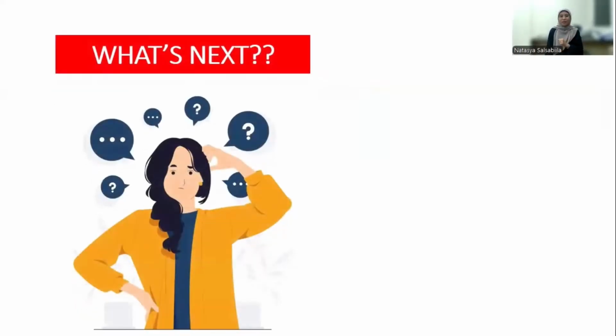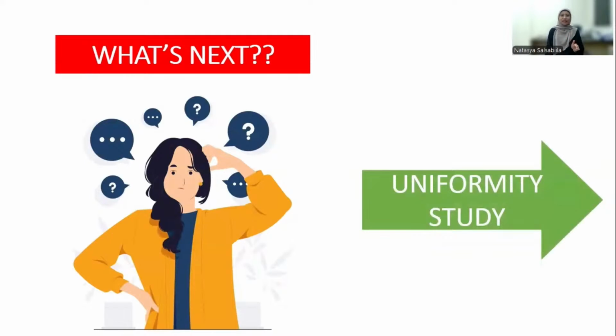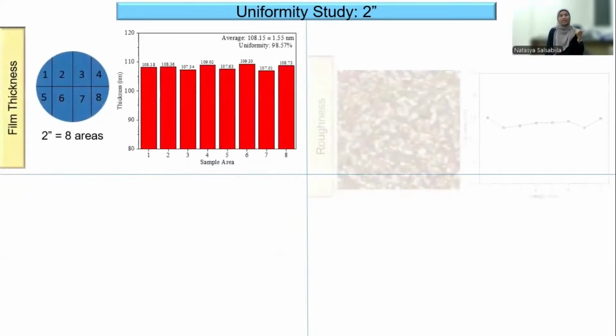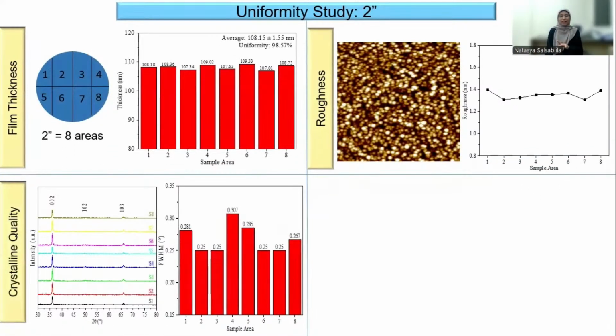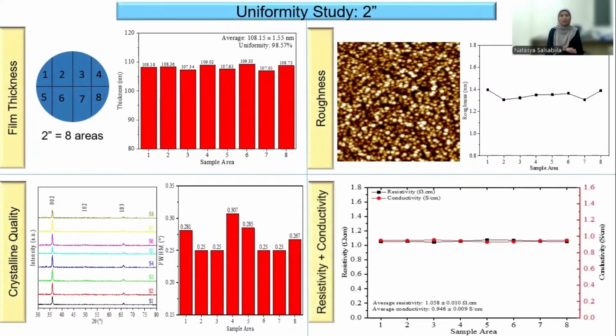Okay, we already know about the properties of AlN with varying rotation speeds, and we know that the best rotation settings are achieved using 10 RPM for both target and substrate rotation speed. Then what's next? Of course, we need to study the uniformity across the entire wafer, right? First, we will see from the 2-inch wafer, from the film thickness, surface roughness, crystalline quality, and also electrical properties, it shows a consistent result across a 2-inch area.